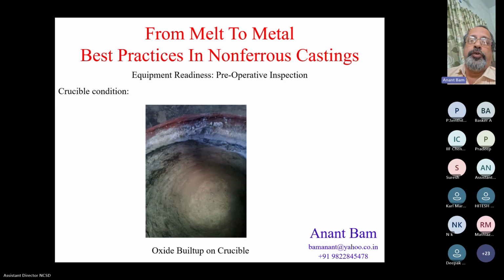You have to observe this photograph carefully. On the very top side is the crucible edge, and the white and the gray thing which you observe is the oxide build-up. It's about 1 inch thick oxide build-up on a crucible. It's a 300 kg crucible. The outer edge of the crucible is not visible in the picture. The inner edge of the crucible and the top ring is visible. And inside there is a black line, which is the gap between the oxide and the crucible lining. And in the center, you can see the empty bottom of the crucible.